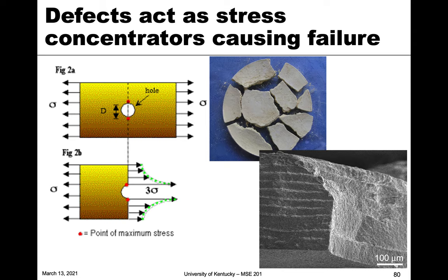This is important because since these materials are brittle, there's no plastic deformation. Instead of deforming when stress concentrates at a defect, they fracture suddenly and in a brittle manner — like if you break a plate. For materials with very little plastic deformation, defects causing stress concentrations more greatly affect the failure of those materials.